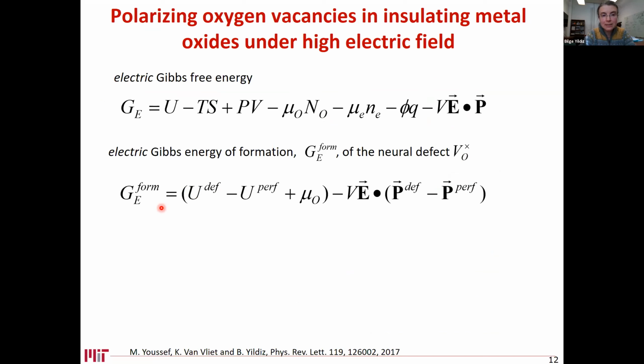We can look at the Gibbs free energy of the system again. So let's look at the thermodynamics again. And beyond the internal energy, entropy contribution, and pressure-volume term, you see terms related to the chemical potential of the species, of oxygen, of electrons. And then these last two terms, which are introduced when you apply voltage, when you apply a potential. So the electrochemical effect is this second to last term, which is pretty much potential times the charge of the defect, which changes the Gibbs free energy.